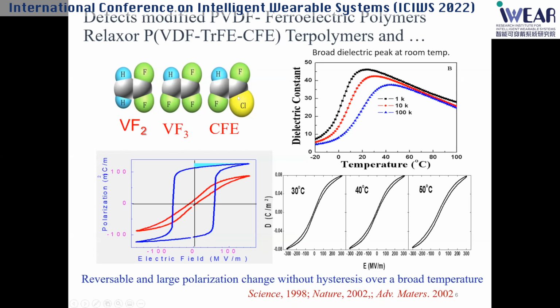We found that by expanding this polymer from the copolymer into terpolymer, with CFE which is a little bit larger than VDF TrFE, we can convert this material into something called relaxor. Basically it has a very large polarization, large and broad dielectric constant peak, and around this peak your polarization has very little hysteresis. This is basically a totally new class of material, and we published several papers in a few journals.